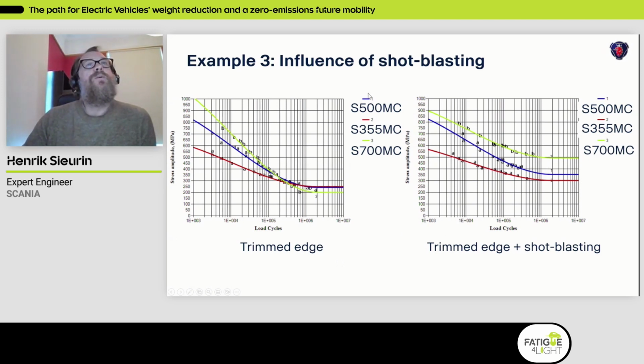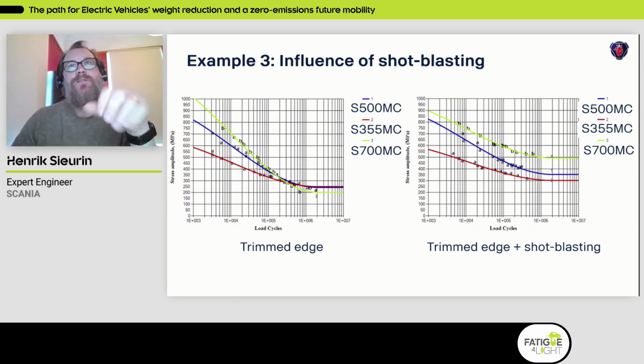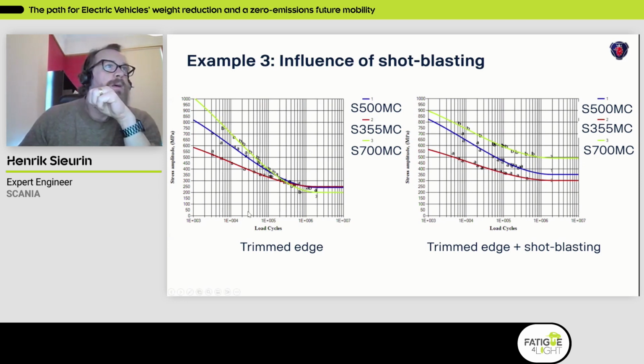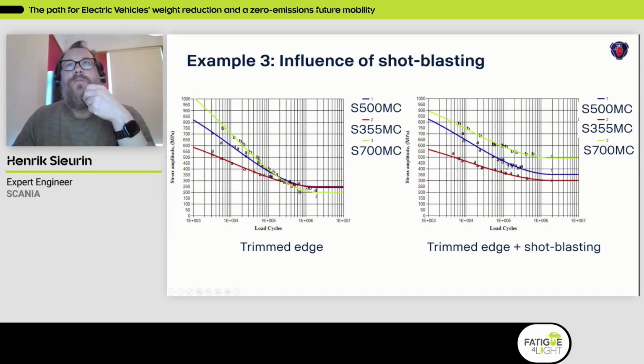So to the left, we compare 355, 500, and 700 MC material at 100,000 cycles. 355 is worse, but the 500 and 700 is similar. But with shot blasting, for the 355 material, there is not a really big difference. This is a relatively soft material. But for the 500 MC, the fatigue strength increases from 370 up to 450. And for the 700 MC, we go from 400 up to 600 megapascals in fatigue strength. So this obviously also makes a big difference.